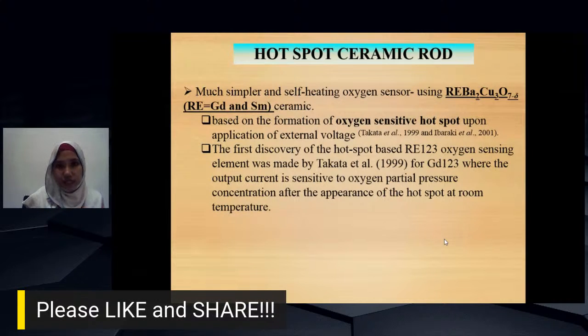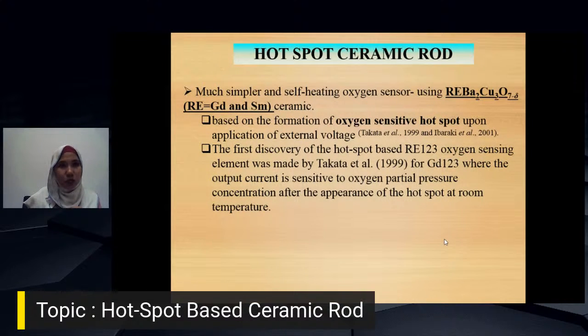The self-heating oxygen sensor using the rare earth barium copper oxide ceramic is based on the formation of an oxygen sensitive hotspot, by applying an external voltage to the ceramic rod to form the oxygen sensitive hotspot.